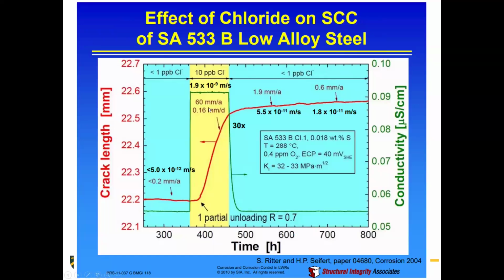So this is a nice poignant example. Again, I like these sorts of experiments because it really highlights what kind of effect this has if you push things to the limit. This is looking at, I don't even know what the steel is, 533B. Don't ask me, I'm not sure what that is. But essentially it's an experiment where they added a whole bunch of chloride and then they removed it again. I say a whole bunch, it's actually only 10 ppb of chloride. But you can see how quickly that crack length grew, and then how quickly it, I don't want to call it stopped. It looks like it's still going to some degree. You didn't reverse things entirely, but it's a lot less once you remove that chloride from the bulk water chemistry.